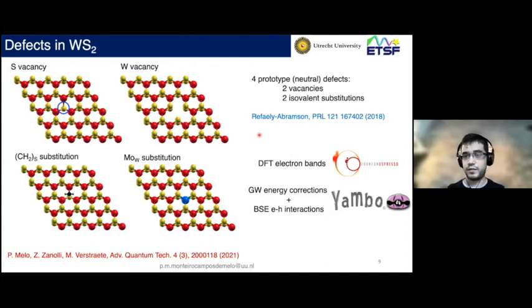We stayed with neutral vacancies, since it was reported in previous work that charging the defect should just shift rigidly the defect states, if there are any, in the mid-gap region. And so the energies of the optical signatures would shift, but the number of features would have to remain the same.